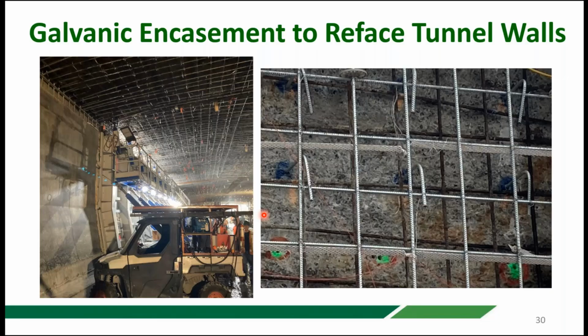And on this particular project, they're using galvanic encasements for the walls, which show you a couple of photos here, as well as for the underside of the ceiling, the roof of the tunnel. And so the photo that you see right now on the right is a picture of one of the wall sections after the hydrodemolition is done. And you can see the prepared concrete surface. In some places, the outer layer of reinforcing steel is exposed. In some other cases, it's not.